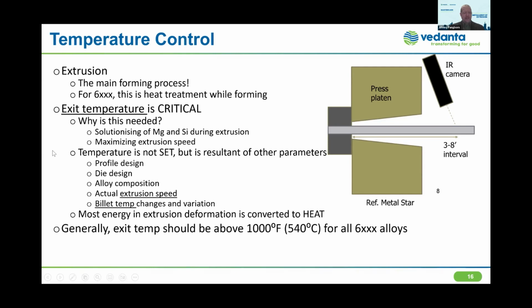Exit temperature is not set. It's a resultant of other parameters. There are some software packages and so forth that will provide feedback from the exit temperature, and you can set what range you want, and it will change your parameters to achieve that. But really, it's your extrusion speed and billet temperature that are the main variables at the press that are controlling that, combined with the other aspects that are more fixed.